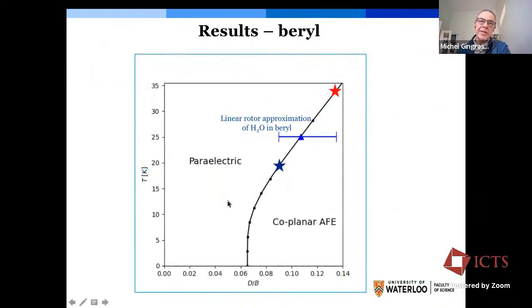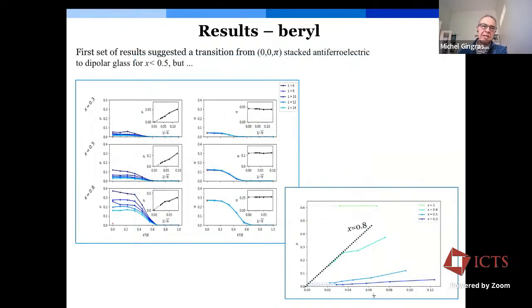So according to our calculations, given the uncertainty on the dipole moment, if all the cages were occupied, we would expect that there would be a phase transition between a paraelectric phase and a coplanar anti-ferroelectric phase in a range of temperature between 35 and 20 Kelvin for these systems. This is not seen. There is, as I mentioned, a saturation of the dielectric permittivity. And one of the questions that we ask is what's the role of finite concentration of the cages occupied by water molecules?